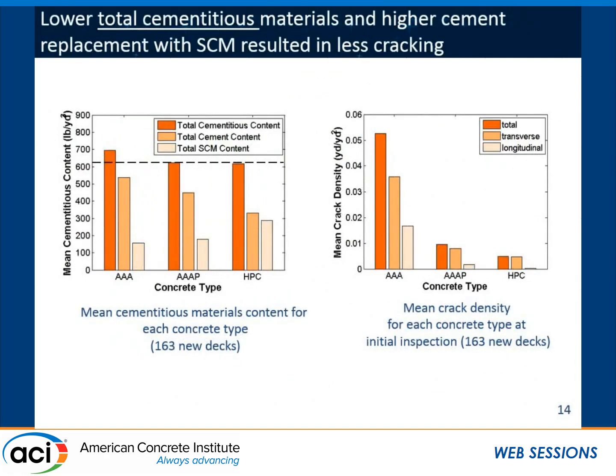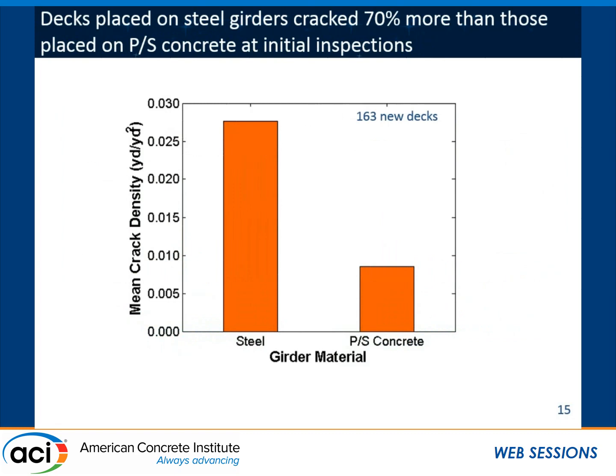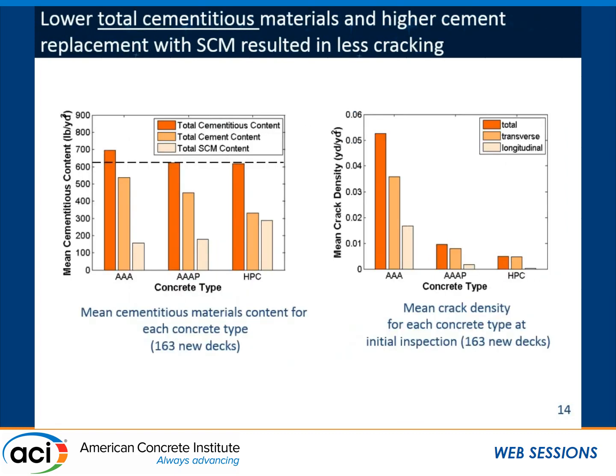This is the same graph that we saw before. This one shows the total cementitious material content, the total Portland cement content, and the total SCM content. So the light orange and white add up to the dark orange. We can see the AAA that cracked the most had the highest amount of total cementitious material. And between the other two, the HPC, which cracked the least, had higher SCM replacement in comparison with the AAAP. So it looks like lowering the strength helps. It looks like capping the maximum cementitious materials is good, and also replacing, within reason, Portland cement with SCM is helping. That's primarily through reducing the heat of hydration and reducing thermal contraction of concrete.